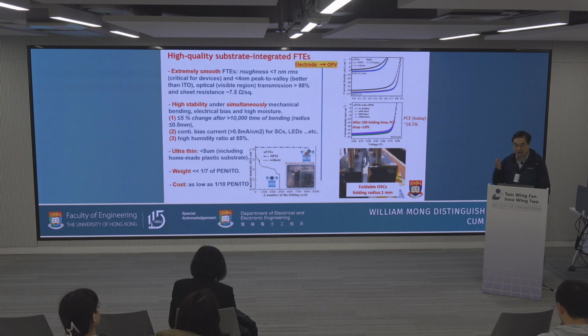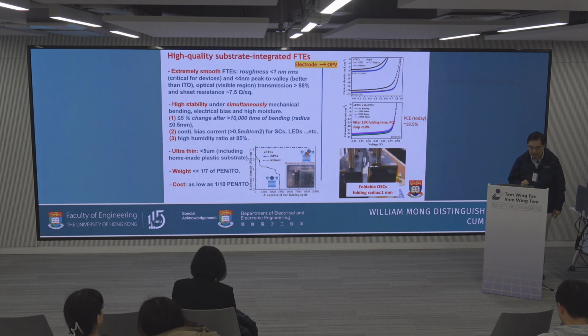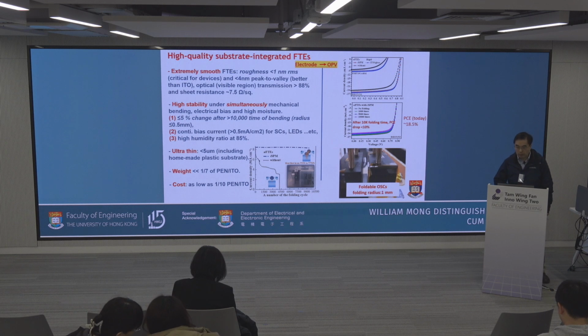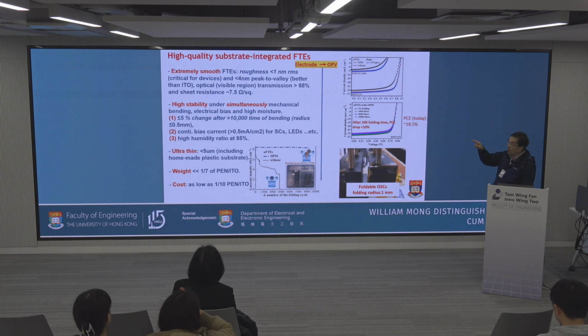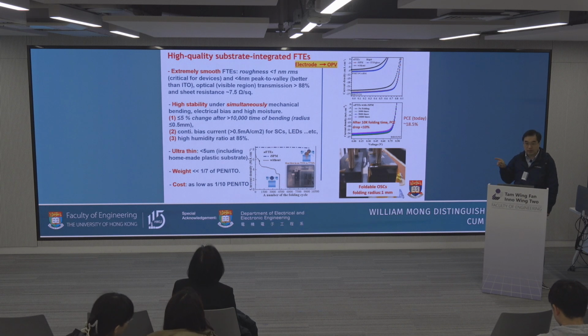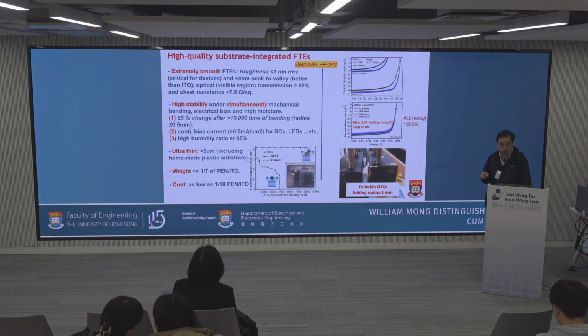Again, our electrode is a substrate-integrated composite electrode. We try to benchmark ourselves, beating ITO. We can make the electrode with smoothness less than 1 nanometer, roughness peak to peak less than 4, transparency over 88%, and sheet resistance of 7.5 ohm, which is pretty good compared to ITO.